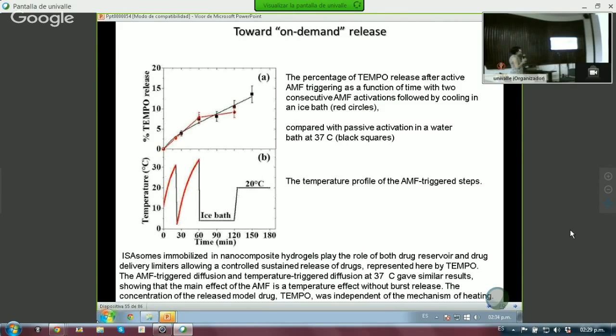So what this means, if you want to go back to the ISAsomes, is that when they are immobilized in this hydrogel, they play the role of both drug reservoir and drug delivery. And so they will allow this sustained release of the drug as a function of time. And the AMF triggered at 37C gave similar results. So the main effect of the AMF is a temperature effect without any burst release. So anyway, it's feasible to do what we were planning on doing. And the concentration of the released model drug was independent of the mechanism of heating, since we have in both cases the same results.